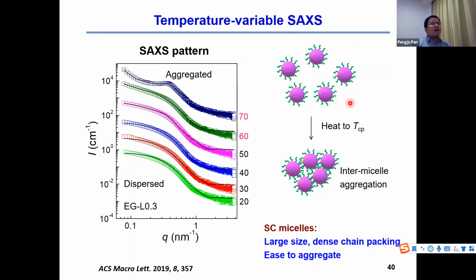Based on the SAXS analysis, we can explain the thermo-responsive behavior of the copolymer controlled by stereocomplex crystallization. In the mixture of both L and D copolymer, stereocomplex crystallization leads to the formation of a larger micelle. Larger micelles will have stronger van der Waals attraction force between each other, so they can aggregate and show a lower cloud point.